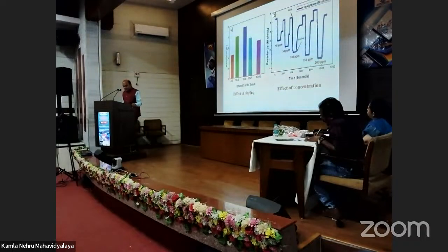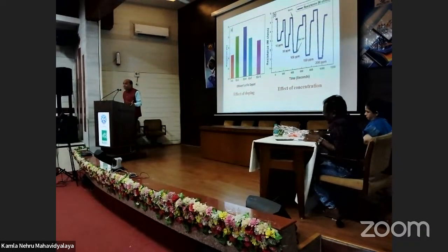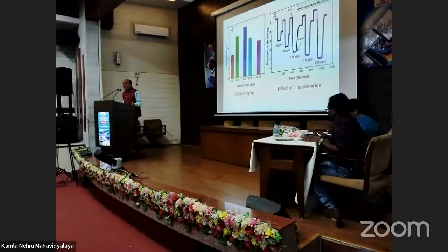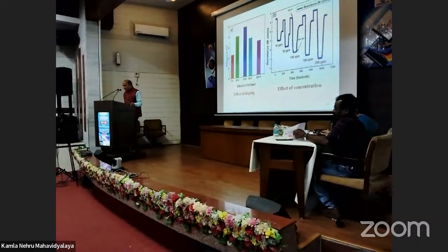That is the different percent of Sn doped zinc oxide and their response time. It has been observed that 5% Sn doped zinc oxide shows very good response. Effect of concentration, if you look, at 5% we have tested from 10 ppm to 200 ppm.